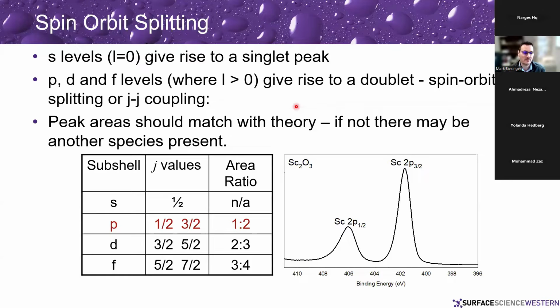So what I mean by that, for say a p orbital, you have j values of 3 halves to 1 half. The number of electrons are 4 to 2, and so we should have an area ratio of 2 to 1. And if we look at something like the scandium 2p peaks, we have an area ratio of 2 to 1 for the 3 halves to 1 half peak. The d orbitals, you'll have an area ratio of 3 to 2, and for the f orbitals, it'll be a ratio of 4 to 3. And if it's not that, then something else is going on.